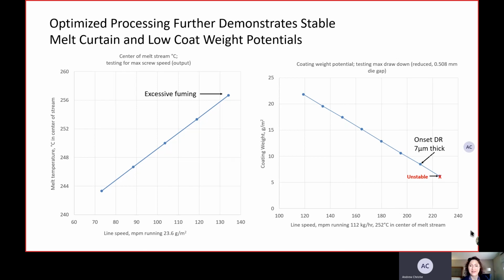Moving on to the second graph, we do a drawdown study where we maintain that extruder output and increase the line speed, taking away that polymer, going faster and faster. As we do that, it will thin the coating down. You can see the coat weight started off at about 22, and then it decreases as the line speed increases at constant extruder output.